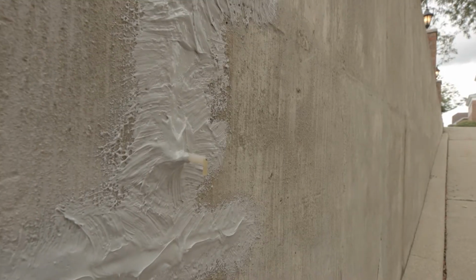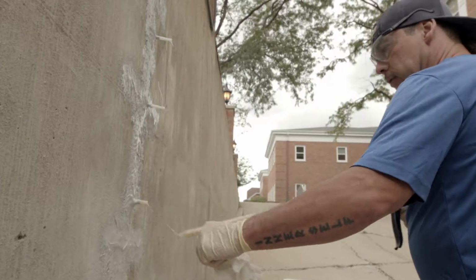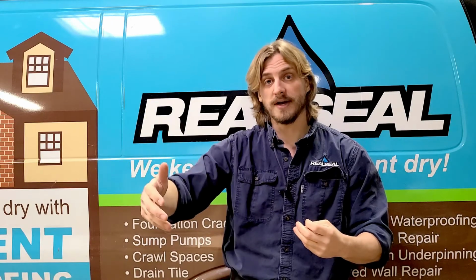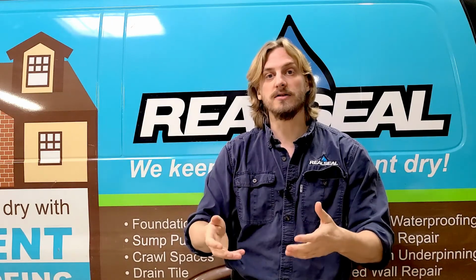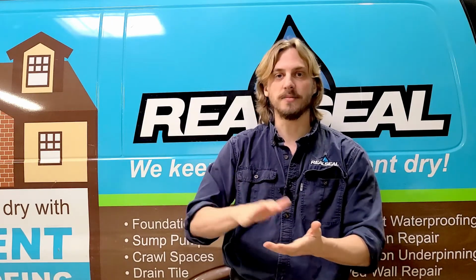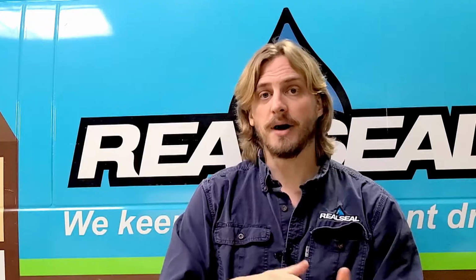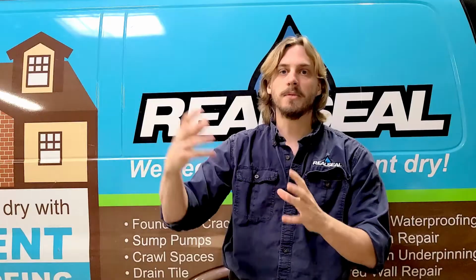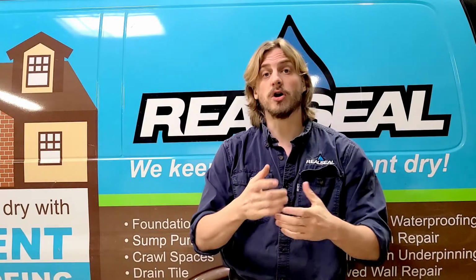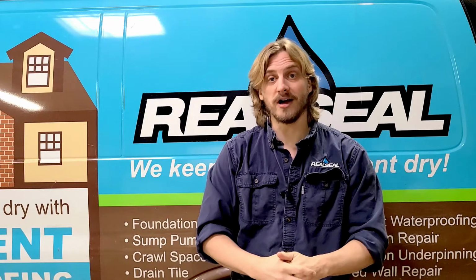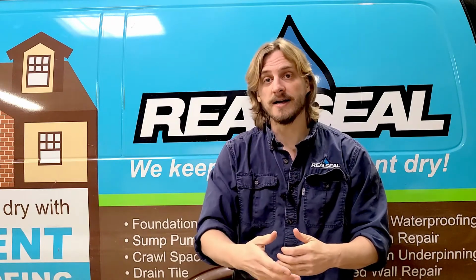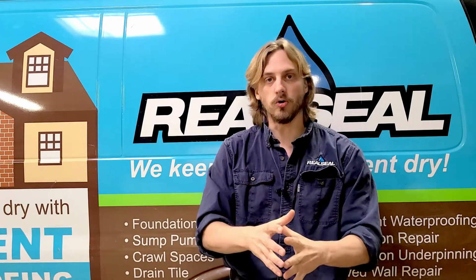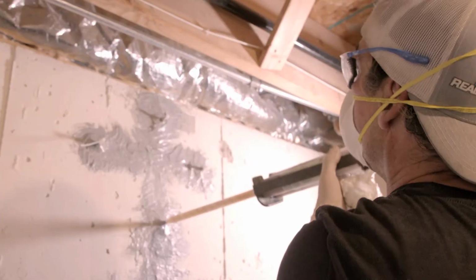However, it can leak out the back into voids that are formed by the dirt from poor water management, which can create a need to come back and re-inject the crack to make sure that it's filled up all the way. A polyurethane injection, while it solves that problem, is a much weaker repair, and you're more often coming back to re-inject the crack or even fix it from the outside because the foam didn't hold.